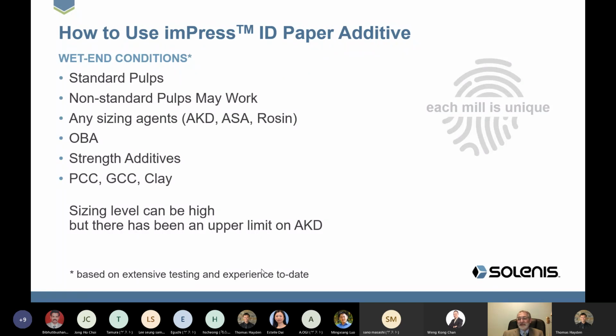And so what do we want to do? Another variable in the paper is the wet end conditions. And you can use any type of standard pulp or even non-standard pulps. You can use any type of sizing agent, the ketene dimers, the liquid ketene dimers, the ASA or rosin, all can be used at the wet end. You can use optical brightening agents at the wet end. You can use strength additives, or you can use PCC or GCC or clay or other fillers. It makes no difference. Our product still works very well.